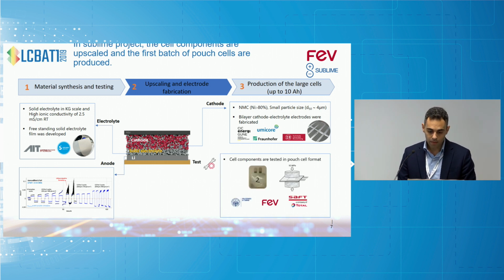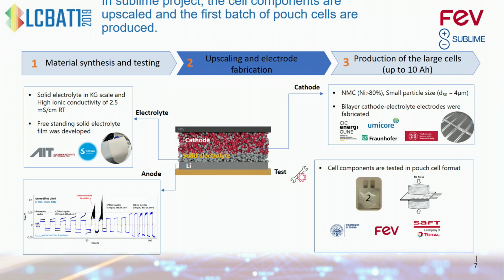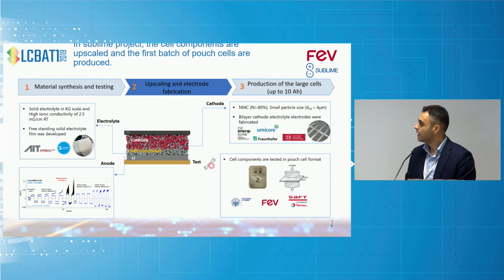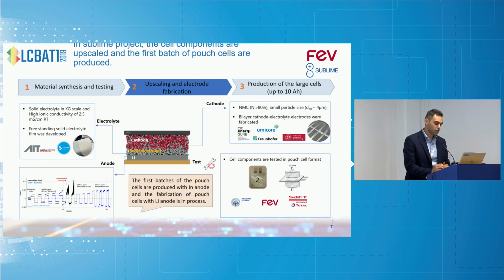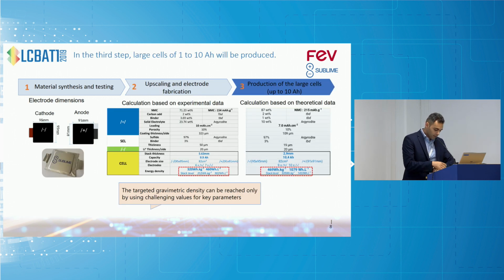And at the moment, the first generation of the pouch cells have been produced and are being tested. This is very new, very recent activity. But for the first generation of the cells, this lithium anode was not ready yet, and we used an indium anode. So the first generation of the cells are being produced with the indium anode, and now that we have recently achieved these promising results for the lithium anode, the next generation of the cells will be produced with the lithium anode.